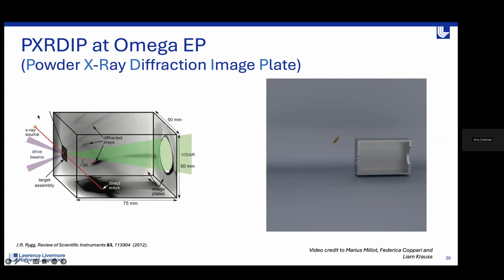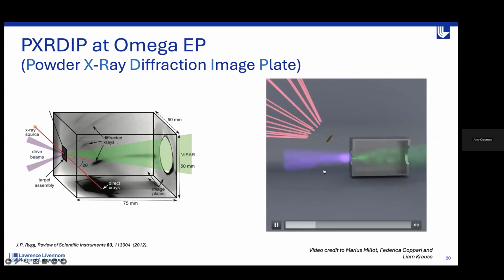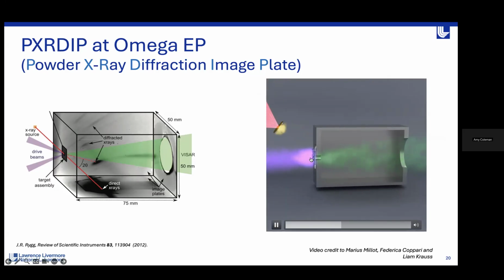So this is the foil. We have some number of lasers pointed at this foil, and we drive it at the right time so that we can send our X-rays through our compressed sample and take a snapshot of what is going on in our sample at that moment. The X-rays are coming in, they're diffracted by the sample, and the diffraction is collected by the image plates on the walls of this PXRDIP. I've got a small video here which is illustrating that. So we've got our laser drive. You can see our target being ablated there at the surface. There's all that blow off. Our X-rays are coming through, and we're collecting all of the diffraction data on the walls of this PXRDIP box here.